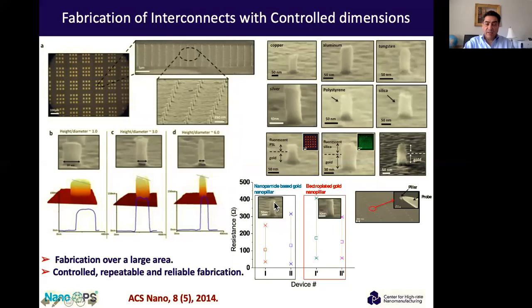And to check the resistance, we made an interconnect using this printing process using particles, and it's shown here. And then we made the electroplated gold, the same size, same dimension. And you can see that the resistance is pretty much the same between the two. This is using a probe inside an SEM that allows you to measure a resistance of a 50 nanometer pillar. That's the one you see here. So it shows that you're actually getting pretty much the same conductivity using this process.